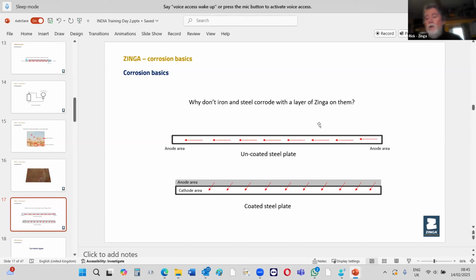So corrosion is not that hard to understand when you look at it from this point of view. It's very, very basic. So yeah, all coatings, it doesn't matter what they are, all coatings are barriers. Even many zinc coatings like zinc epoxies. From a chemistry point of view, it's a complete waste of precious zinc dust, because they just sit there as a barrier to stop moisture. They're not putting any current into it. Only Zinga, hot dip galvanizing, zinc thermal sprays, they're active. And they're all putting the current into the steel.